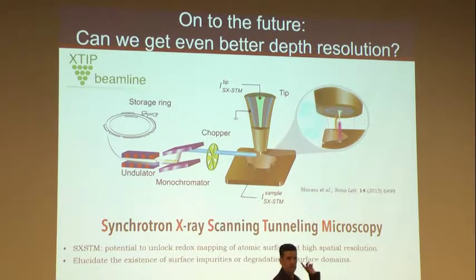And if you have any questions of how that works, you ask him. But the idea here is that you have an STM measurement that is coupled with the photoelectron generation of a sample when you irradiate it with a beam that is at a given absorption edge. You can do it with any absorption edge. We did it with nickel, and we stayed with those layer oxides that I told you about.